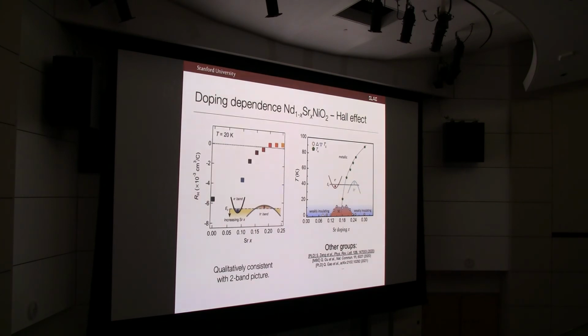Now in terms of the Hall effect, let me skip the details, but in the broad features as a function of doping, this is a slice in temperature, and this is a more broad picture. It's qualitatively consistent with what you might expect from a two-band picture. We don't have enough parameterization to really extract the details like effective masses and mobilities of the channels, but certainly it is consistent with this notion of having two components.